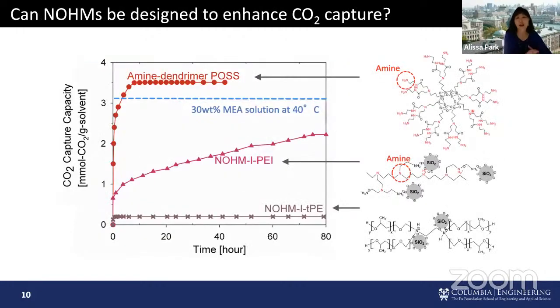So now the only thing we had to do was decorate all these materials with amine functional groups. And as we expected, each time we load more amine into the system, you have a huge increase in CO2 capture capacity. And it was in some cases even better than the state-of-the-art 30wt% MEA solution.